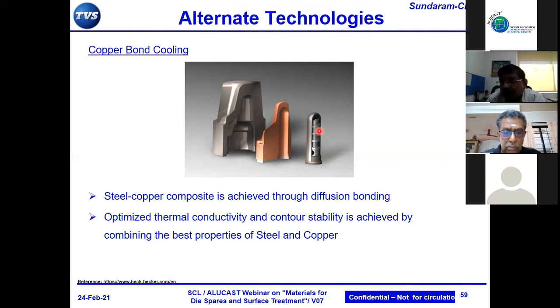Absolutely. Normally in some of the good tool making companies, when the insert is going for heat treatment, along with the insert you have a test bar of the same material tied up with the insert. It undergoes heat treatment and comes out. The coupon of the test bar should be of the maximum thickness of the insert.